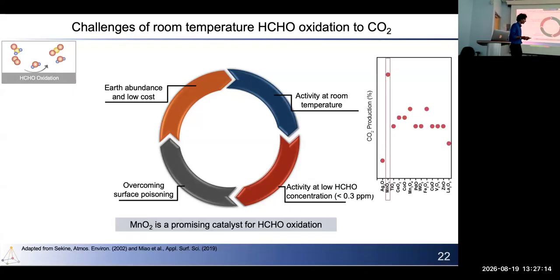So in the literature, there's a lot of work around, again, by trial and error, trying to figure out which catalyst might work for this reaction. And the literature usually points towards manganese oxide for being one of the better catalysts at lower temperatures. But manganese oxide itself comes in about 15 different polymorphs, which have been explored quite extensively for other reactions,